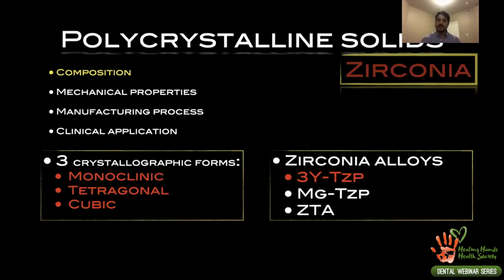Since the material itself is not stable in room temperature, the manufacturers added elements to the zirconia itself. That's why we call zirconia not a pure zirconia, it's a zirconia alloy, because for the dental application, the yttria is added to the zirconia to stabilize it in the specific crystallographic form that we want. The traditional zirconia is stabilized in the tetragonal phase.